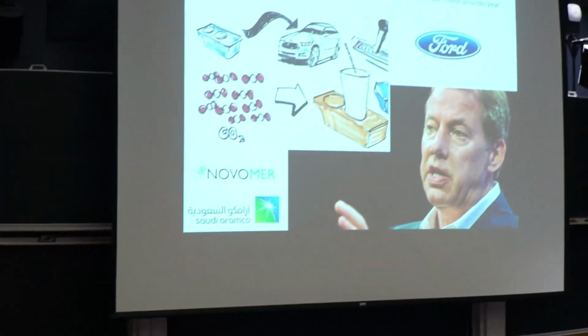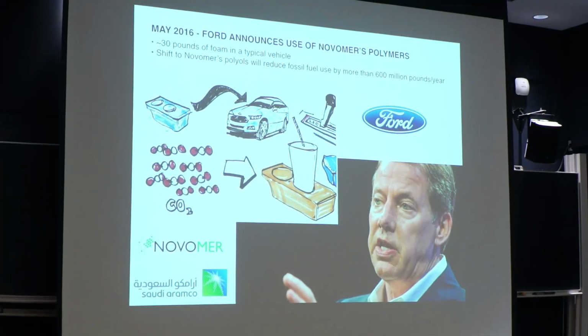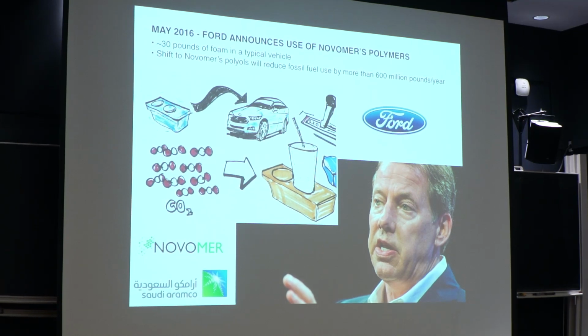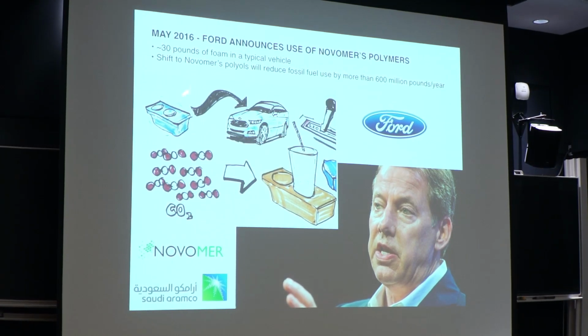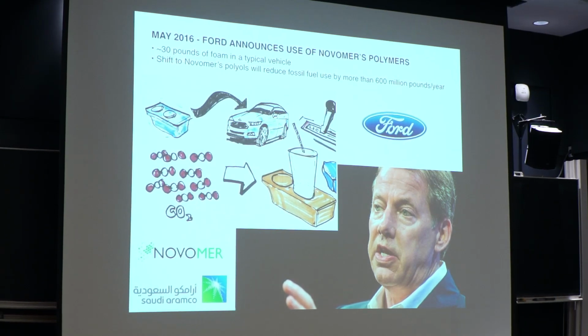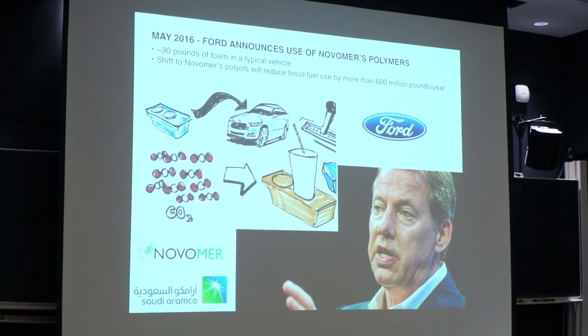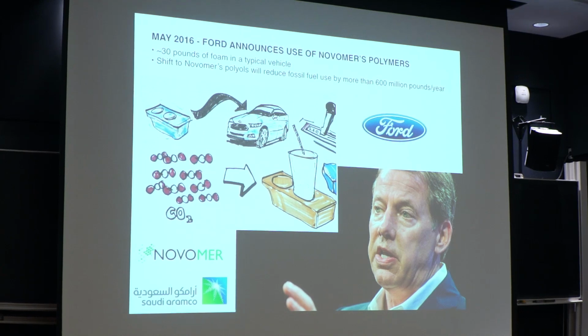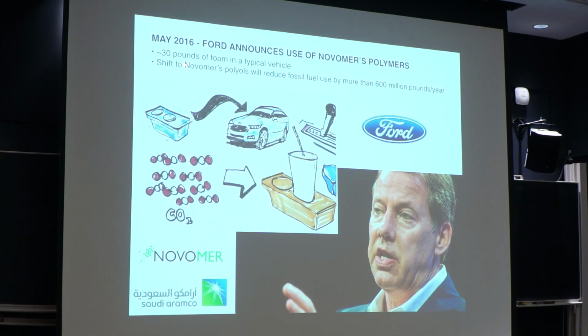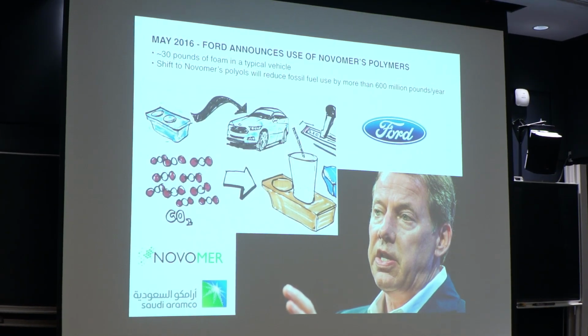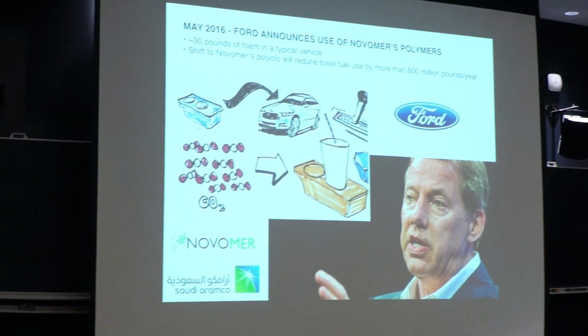So this is in 2016, we got this really cryptic call from Ford, and they said, hey, there's going to be a press release, don't tell anybody, but we're going to announce that we're going to start using your polyols in our Ford automobiles. What you may or may not know is that there's a lot of foam in a vehicle, not just in the seats, but in all portions of the doors and the panels for sound deadening. Each vehicle has about 30 pounds of polyurethane foam, and most of that is based on the polyol.